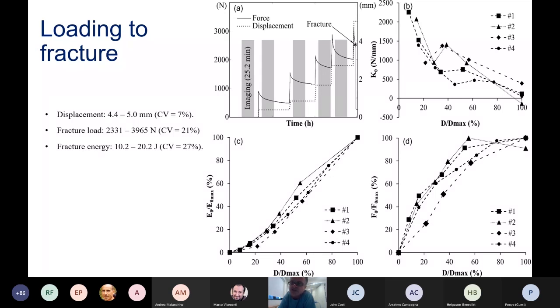The stiffness shows a continuous decrease as the displacement increases. Energy shows a linear increase all the way up to the maximal displacement, whereas the force shows a curvature and a flattening toward the end of the curve.